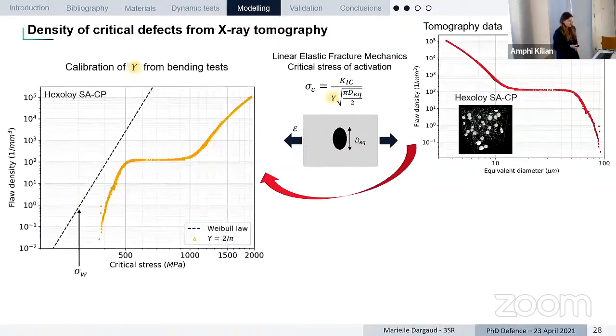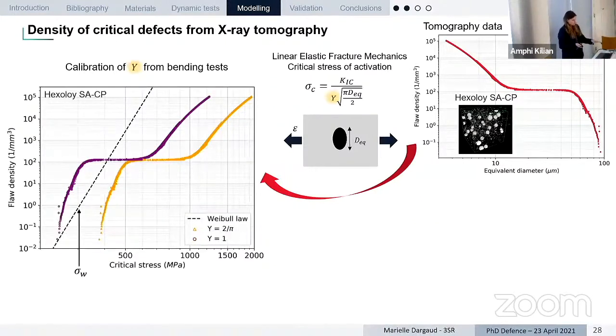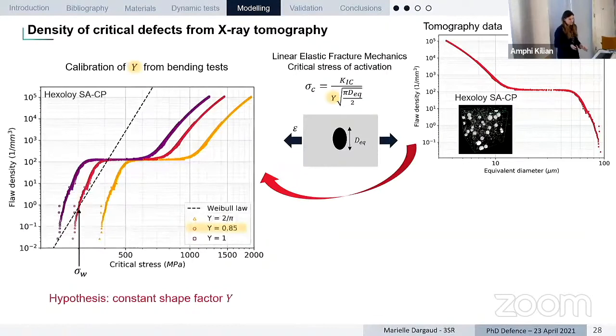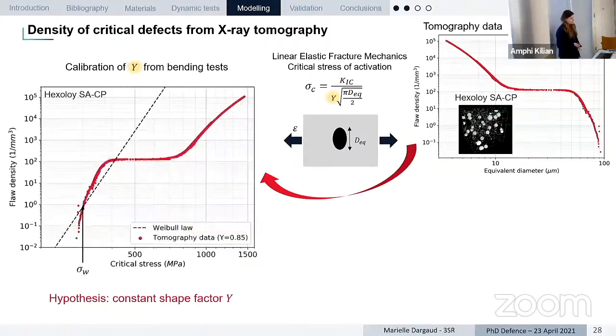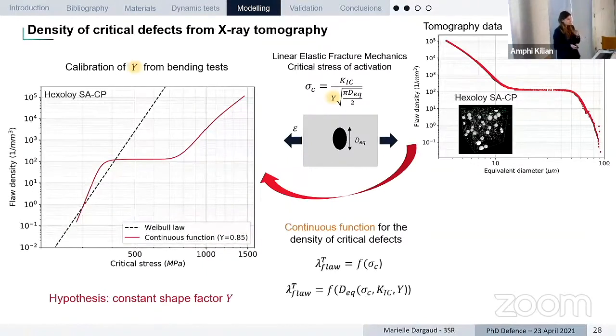Here we have this Y parameter, which translates the shape of the crack. This parameter needs to be calibrated. To do this, we actually plot the conversion of the plot, but for different values of Y, and the best value is the one fitting the data from bending test at the level of the average bending strength. One hypothesis that we make here is that we have a constant parameter Y for all the defect populations. So here we have a parameter of about 0.85. And from this curve, we can now fit a continuous function that we can get explicitly and that we will use and implement in the model.